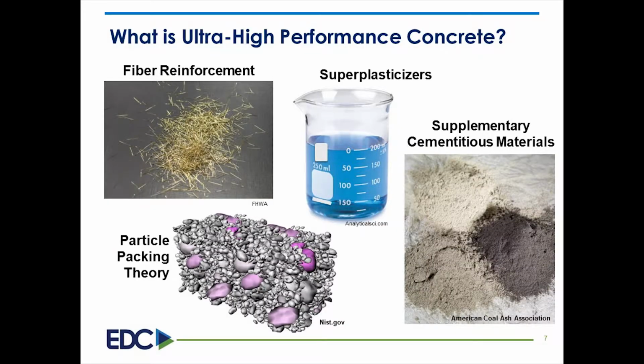Superplasticizers are used to decrease the amount of water that is needed for the mix while still having a highly flowable mix. In addition to the Portland cement, there are supplemental cementitious materials, usually fly ash, and very commonly used silica fume. There's no large aggregate. The aggregate is composed of fine sand and ground quartz, which are formulated to work with the cement using particle packing concepts to produce a very dense, impermeable mix.